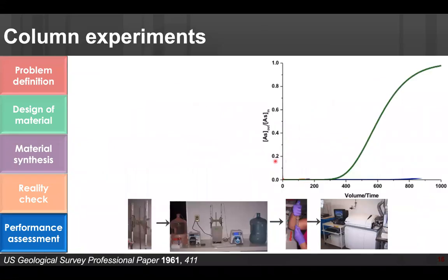The other kind of experiments was the column experiment. When we pack our material in the column, we flow water with some pumps in there, and then we collect the solution after it passes the filter. We make sure that we don't have any particles in there, and we analyze the concentration of arsenic. So what we plot is basically how much time or how much volume we can treat, and how much arsenic is coming out over the amount that I put in at the beginning. A typical column should look something like this.